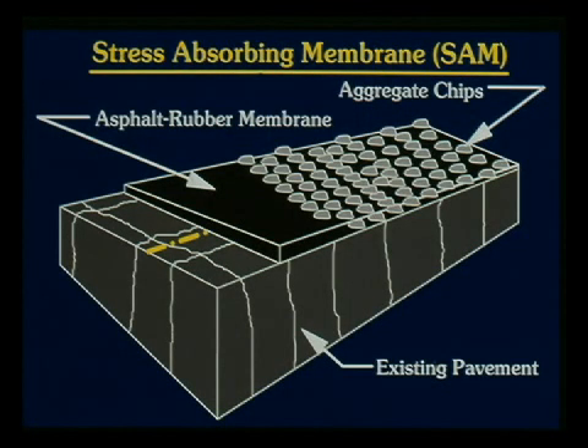Well, for one thing, they came up with a seal coat process, which was called a SAM, stress-absorbing membrane. And the thing about asphalt rubber is because of its high viscosity at high temperature, you can put down a very thick layer of this material before you put the chips down. And we found that would prevent the reflective cracks very well.